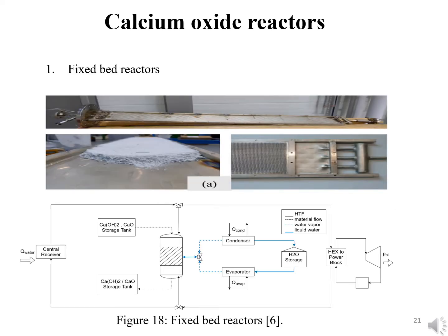The reactors in this research on calcium oxide thermal storage systems are small scale because it is currently in the laboratory development stage. The researchers studied the heat storage efficiency in different reactors, so it is crucial to choose the right reactor. Fixed bed reactors. Fixed bed reactors are widely used due to their simplicity of operations. Because of the limited thermal conductivity of indirect reactors, direct heat transfer reactors are the best alternative.